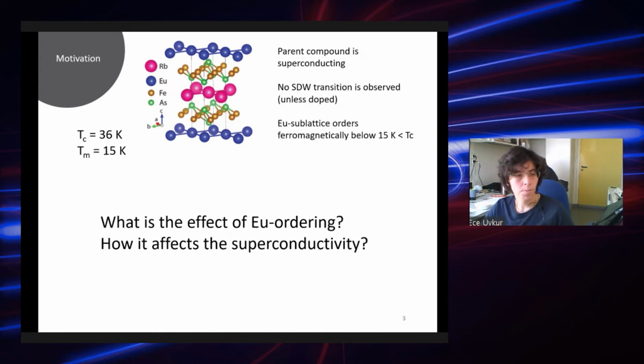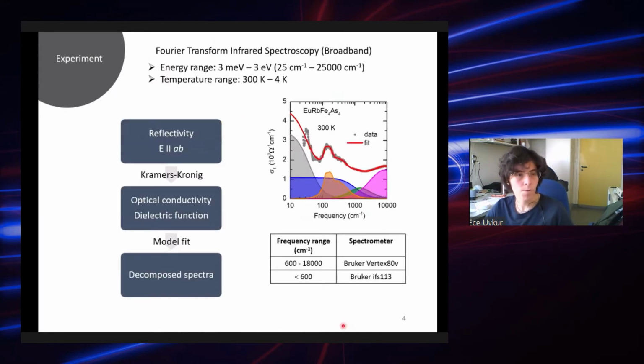So obviously there are a lot of experimental methods to tackle these questions. But being an optical spectroscopy group, we wanted to look into these questions by means of Fourier transform infrared spectroscopy. I put this slide because it's maybe not so familiar to everybody. Basically, we measure the reflectivity of our samples in a broad frequency range, and this indeed covers quite a broad range. I put two energy scales here, so you can choose whichever you want to use. In the optical spectroscopy community, we always use the inverse centimeter. Our temperature range was from room temperature to 4 Kelvin, which is significantly lower than the transition temperature of the system.